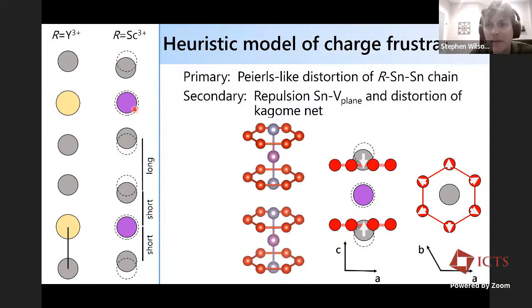One way of thinking about this is that you can put a smaller scandium ion in the system. And when you do, if you look along the chain, the tin atoms come in and want to bond, and you form these trimer units. And when you form this trimer instability, you form a chain of long and short bonds. So you can imagine I have a trimer here, and as each trimer forms, the tin atom tries to get pushed into the center of the Kagome net, inside of a hexagon, and there's a steric effect. The tin atom wants to go in, and the vanadium atoms want to move away.